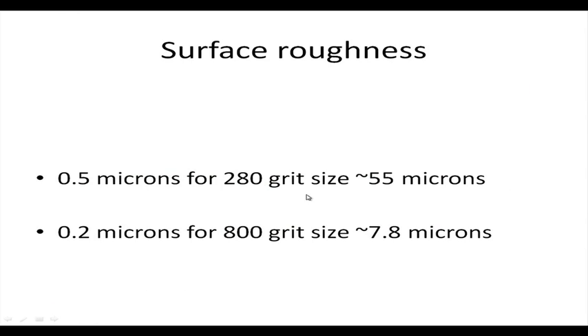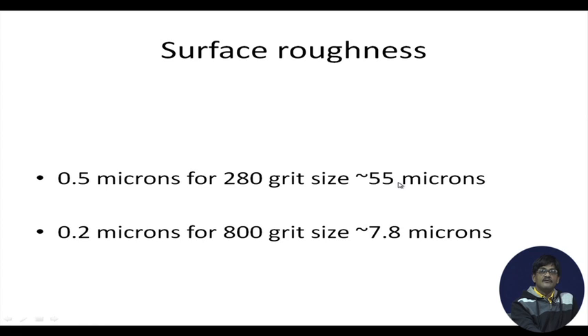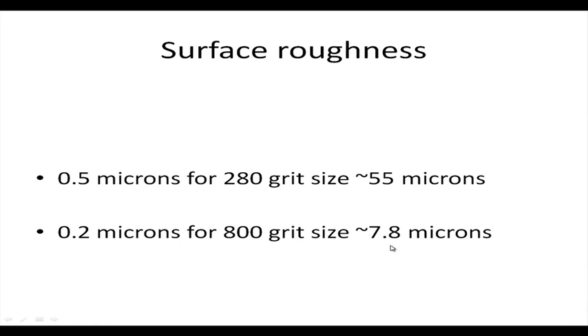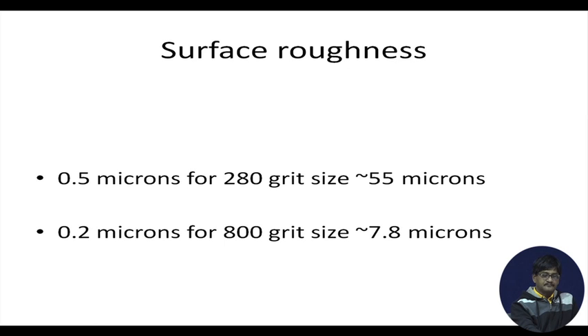So, surface roughness, some data. If you have 55 microns as the grit size, which corresponds roughly to 280 mesh size, okay, then you will get a roughness RA value of 0.5 microns. If you have 7.8 microns as the grit size, corresponding to 800 mesh size, it will give you roughly 0.2 microns. Okay, RA value 0.2 microns.